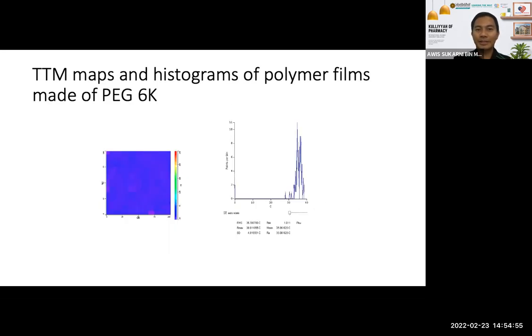And when we move to the PEG 6K film, you can see here there is a similar profile compared to the one that we have in the tablet. So basically all of them are roughly around the purple and bluish color. And if you look here, it looks like it's scattered, but this is because the scale is quite small. The scale is just between 0 and 40 degrees. So that's why it looks a bit scattered. But actually, if you stretch the scale here to 250, it's going to show you a very nice peak. And the value is around 35 degrees.